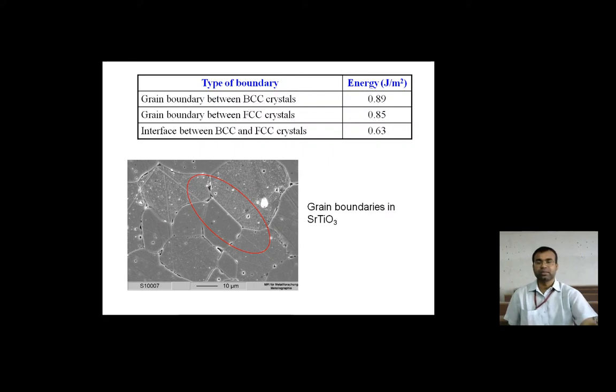grain boundary showing this particular material, and that is how these particular things are notable here, as you can see how these grain boundaries are taking place and how these grain structures are taking place. So the types of boundaries: the grain boundary between the BCC crystals, that energy level is 0.89, the grain boundary between the FCC, that is related to 0.85, and the interface between the BCC and FCC crystal structure, that is related to the